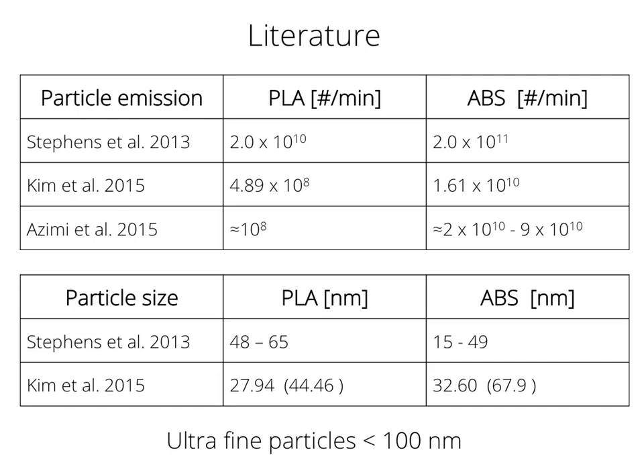The first article that was ever published regarding particle emissions and 3D printers was by Stephens et al. in 2013. Their experiment was quite straightforward. They used a CPC and SMPS, so a particle counter and a particle size distribution analyzer, and placed it in a room where two 3D printers printed with PLA, and during the second stage they added 3 additional 3D printers that printed with ABS. They estimated that PLA must emit about 20 billion particles a minute and ABS about 200 billion particles a minute, but they also clearly stated in their article that further research was needed.